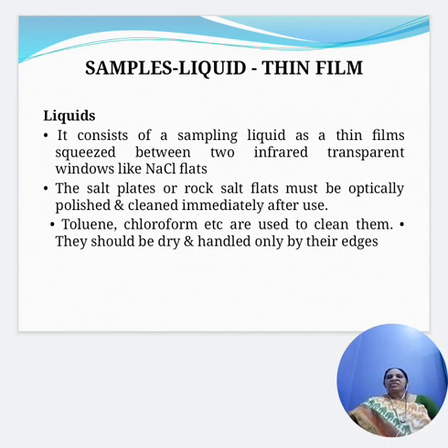Then the liquids. When the sample is a liquid, it consists of the sample liquid as a thin film squeezed between two infrared transparent windows like sodium chloride flats. So you are going to use two windows, and the liquid is placed as a thin film between the two windows. The salt plates or rock salt flats must be optically polished and cleaned immediately after use. After using these plates or windows, they must be thoroughly cleaned and polished.